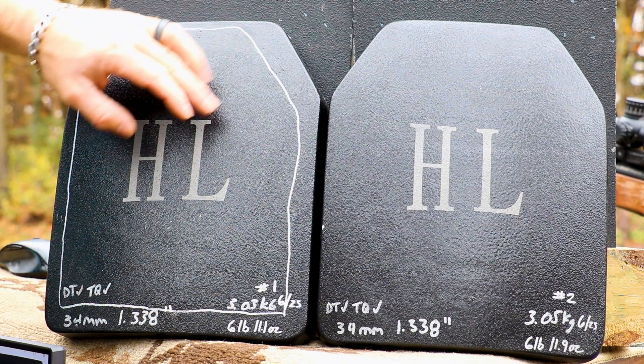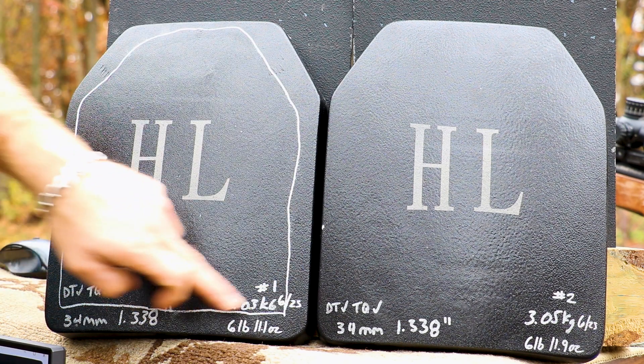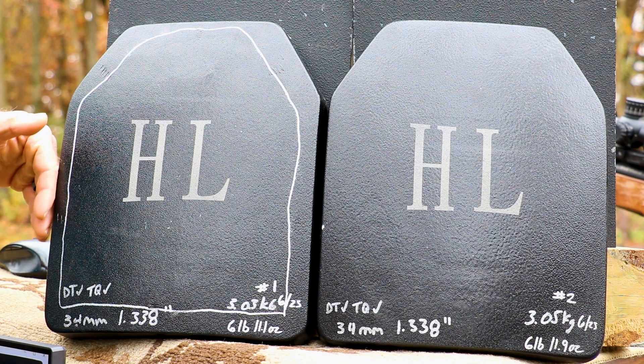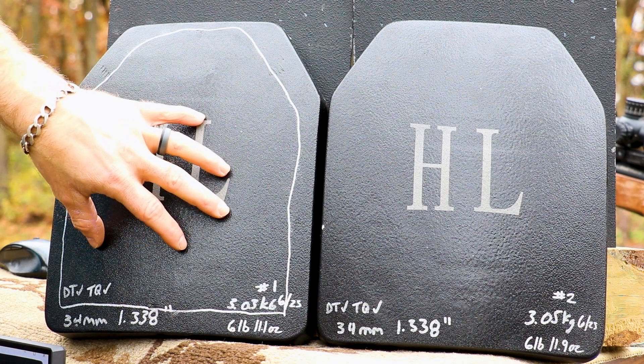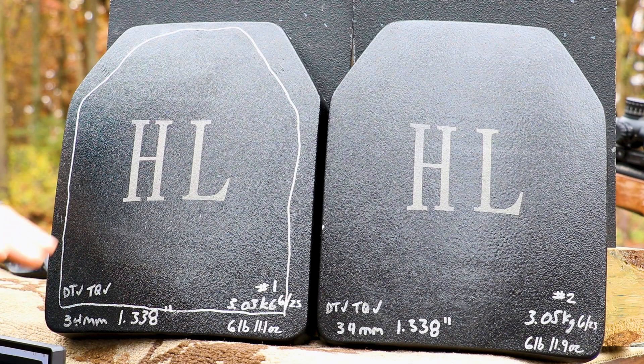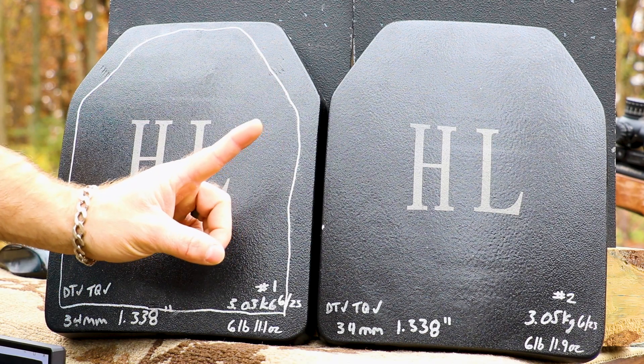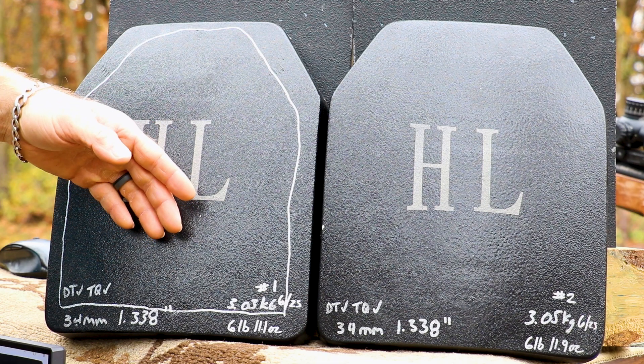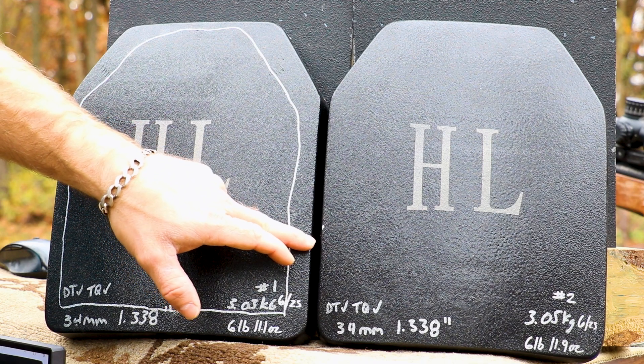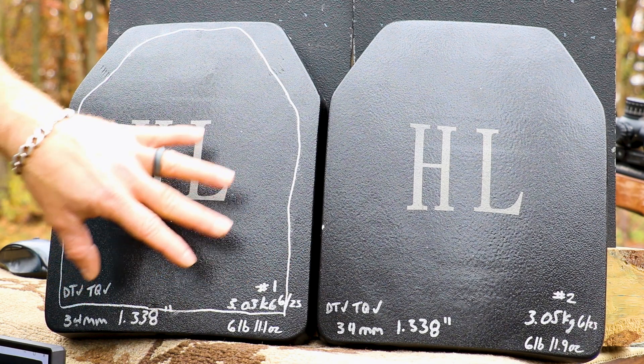On this particular panel, I have a white outline based on the size and shape of our hexagon tiles — it's really hard to get all the way to the complete edge of the plate. What usually happens is there is a foam ring or non-ballistic rated material that makes up the edge; usually behind it is polyethylene all the way to the edge, but this is a foam-like border. We mark that on here so when we're taking shots we stay inside the ceramic for that threat profile. For all NIJ protocols, they will not shoot closer than two inches from the edge. For level four, it's only one round of M2 AP and it's center of mass. If a manufacturer's plate is lighter than a competitor's, look for specific wording to ensure the ceramic strike face extends all the way to the edge, or that the manufacturer calls out a non-ballistic foam ring so you know you're getting less coverage for the given size.